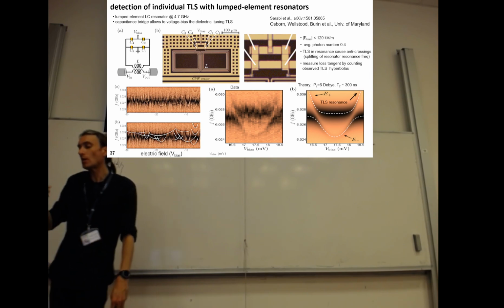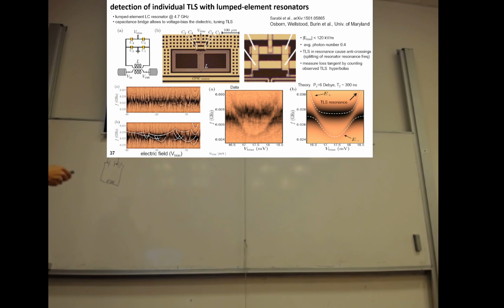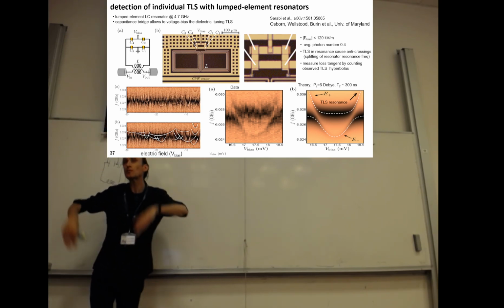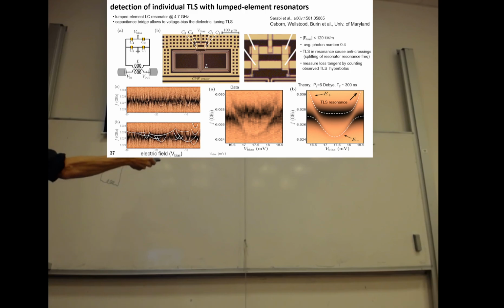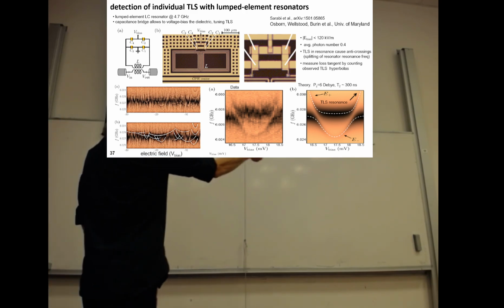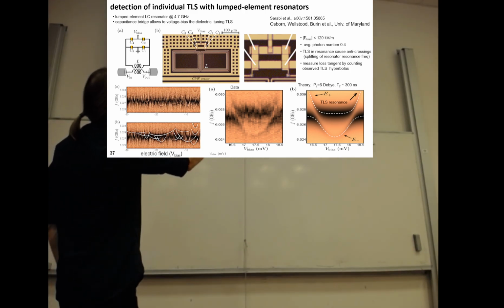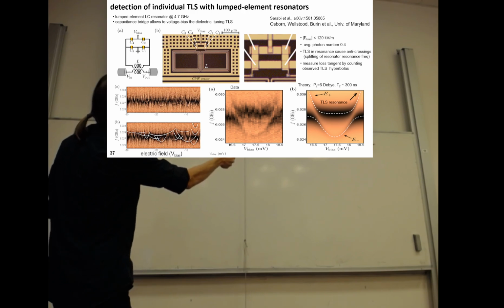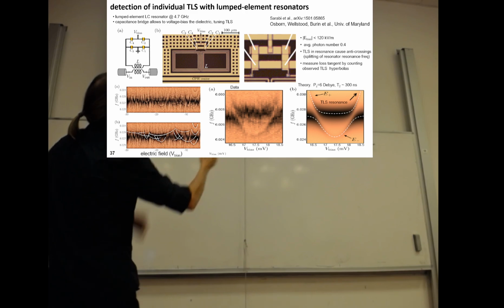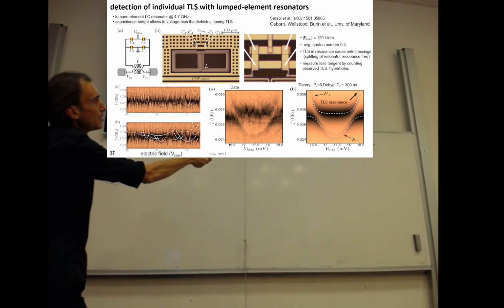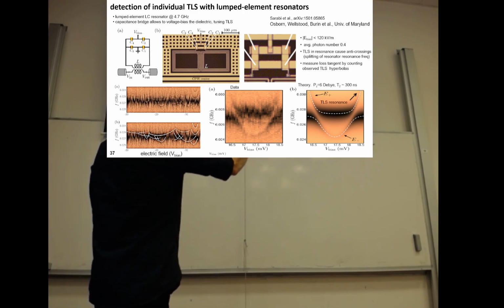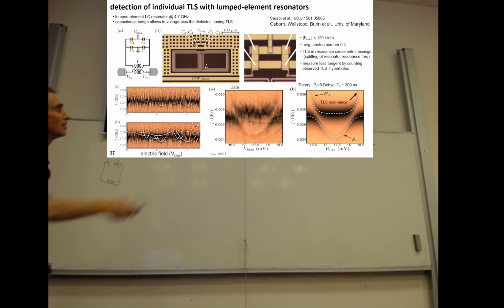Yeah, you can focus on these hyperbolas here and really see, okay, these are really avoided level crossings. You know, avoided level crossings occur when you have 2 quantum systems which are coherently coupled. Here you would expect a horizontal line, but then the TLS comes through resonance, and at the point where both have the same energy, they have the level repulsion, and this shows up as these anti-crossings here in both places, and you can use this to fit the TLS properties.